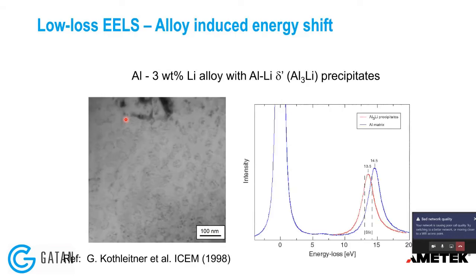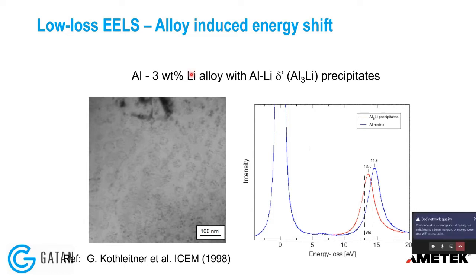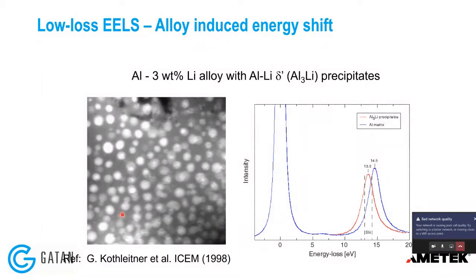Here is an example looking at aluminum-lithium precipitates. The matrix is made of aluminum, but there are very small precipitates of aluminum-lithium. You see nothing in a regular TEM image because lithium is very light, but even this small amount of lithium changes the electron density, producing a change in the plasmon peak. By collecting only the electrons around that plasmon peak energy, you get an image in seconds that highlights the presence of these precipitates — no other available technique could give you this information so rapidly.